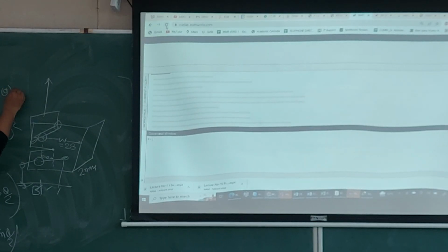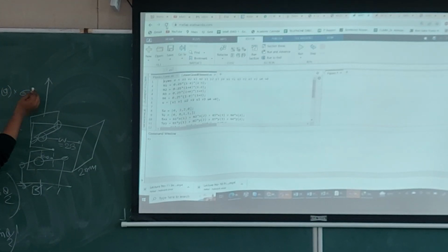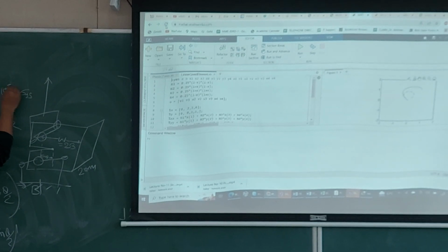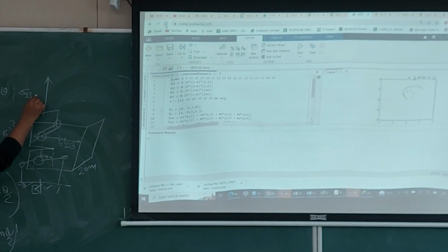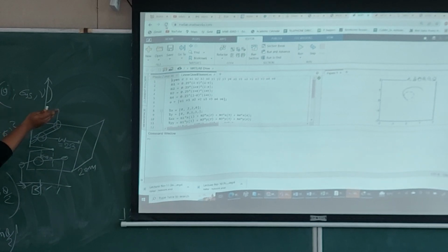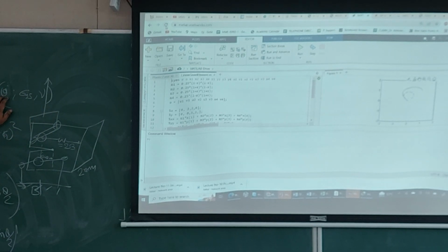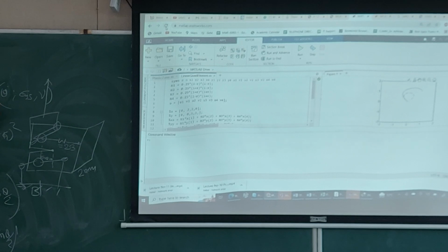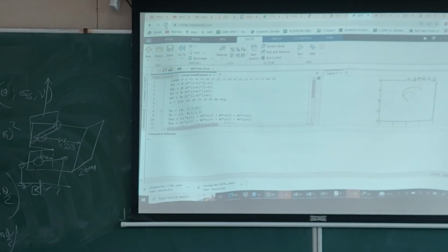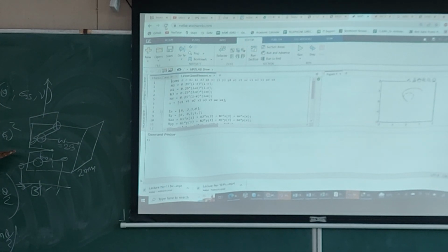So what will you have? You will have a function of r and theta equal to this, right? So then you can find r is equal to some function of theta into sigma ys, and also mu will be there. I shouldn't call it a function, those are constant values. Theta will be changing, theta will be a variable, and you will get different r values. This r value defines when plasticity has occurred, right? Because we are using von Mises criteria.